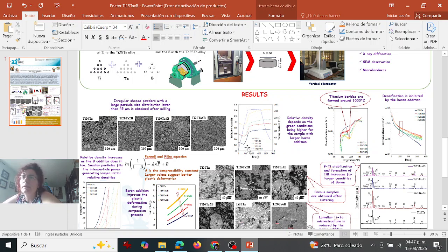If we have a look at this graphic where we have the relative density versus time and temperature, and we observe these curves, the dilatometric curves, we can see that the relative density depends on the green conditions, being higher for the samples with larger boron addition.